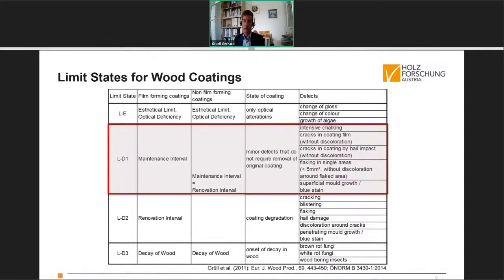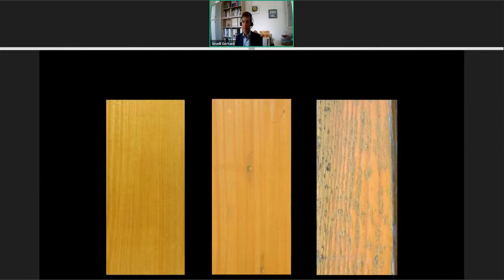In our research work, we focused a lot on the maintenance intervals, on maintenance work, which is based on this definition of limit state of maintenance interval. And that's why I want to elaborate a little bit more on this stage. If we now look at real wood surfaces in natural weathering, the left one is a sample in the original state before weathering, and this is somewhere in between and somewhere in the end of a weathering test. You see different stages of degradation of the coating. There is a brown varnish on top of this soft wood surface, and you see different levels of degradation.